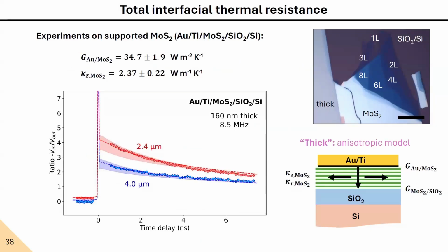Not very easy. This is a very relevant point, because the lock-in amplifier spits out these two signals, the in-phase signal and the out-of-phase signal. The in-phase signal, in principle, is more dominated by the pulse heat diffusion. So the pulse heats up the sample and diffuses, and the out-of-phase signal is a result of the modulated heating. So we are performing heating in a sinusoidal fashion, but it's pulsed. So the heat increases, decays, increases, decays, and eventually this modulation leads to a delayed thermal response, which is what we measure in the out-of-phase signal.